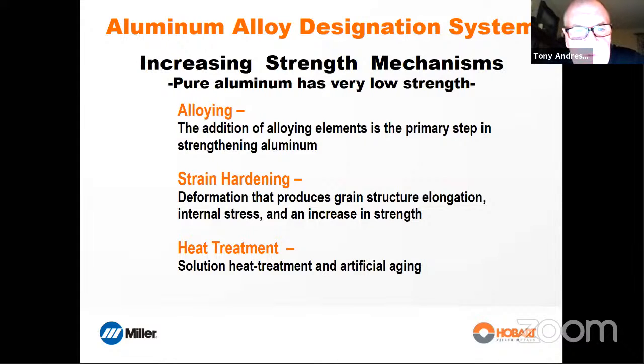So one of the first things they did after coming up with a viable method of extracting the aluminum metal from the ore was to figure out how they could make it stronger. They knew it had great corrosion resistance, it was lightweight, but didn't have great strength. So they found by adding alloying elements to the aluminum, we could increase its strength substantially. One of the first ones were the 2000 series, the copper alloys. Duralumin is a name that some of you may have heard. It's one of the early aluminum copper alloys, and everybody used to say it was unweldable, and it was pretty close to being because of the level of copper in the alloy that they put in to strengthen it.